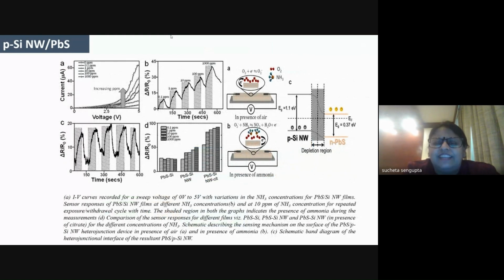And what we measured is we tested it for ammonia sensing in the resistive mode. What we saw is that with increasing ppm of ammonia, the current in the IV curves increases, so the resistance changes, consistent with varying the concentration of ammonia, and it is reversible. It comes back to its original value once the ammonia is switched off. And most interestingly, of the three samples that we had, that is one over the silicon substrate, one over the silicon nanowires, and one with the silicon nanowires in the presence of complexing agent, the last one shows the maximum